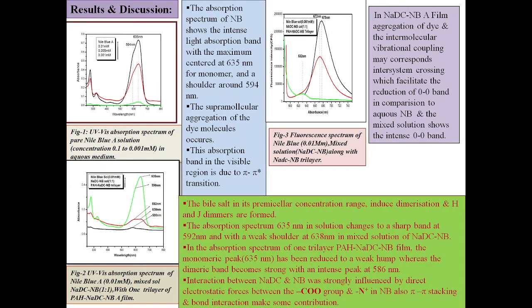Now let us discuss the results. The absorption spectrum of NB shows an intense light absorption band with a maximum centered at 635 nm for the monomer and a shoulder around 594 nm. The supramolecular aggregation of the dye molecules occurs, and this absorption band in the visible region is due to a pi to pi star transition. The bile salt in its pre-micellar concentration range induces dimerization and H and J dimers are formed.